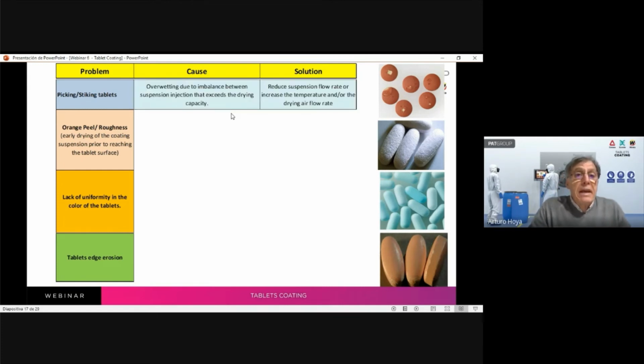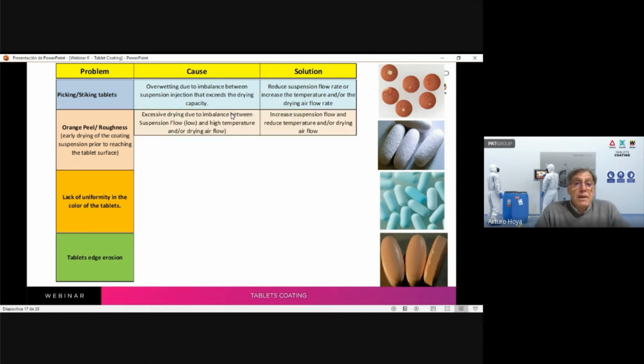So picking, the cause is overwetting due to an imbalance between the suspension injection that exceeds the drying capacity. We said this before. So what is the solution? Reduce the suspension rate, or increase the temperature and or the drying air flow rate. So you compensate. Orange peel means excessive drying due to an imbalance between suspension flow and the high temperature or drying air flow. So what you need is to increase the suspension flow and reduce the temperature.